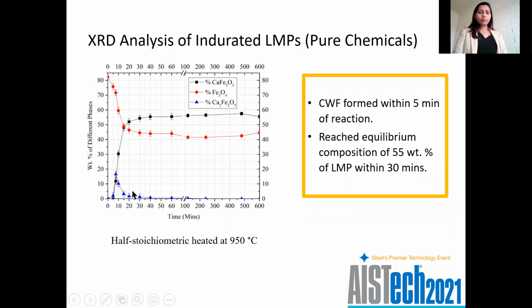So these are the samples that were indurated at 950 degrees centigrade. The samples were pure laboratory chemicals without any impurities in them, 99% pure. And the LMPs were found to produce CWF within about 5 minutes of reaction, and we saw about 55% of CWF within 30 minutes of reaction, and that is near the equilibrium percentage predicted by the phase diagrams.